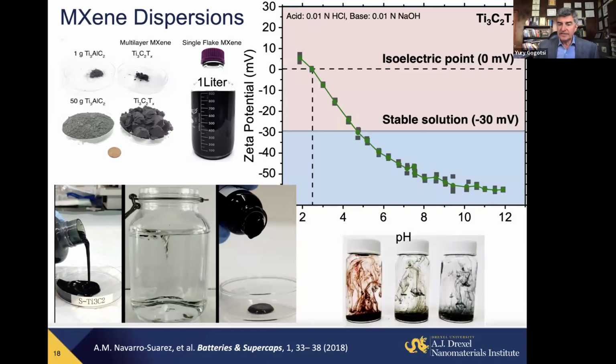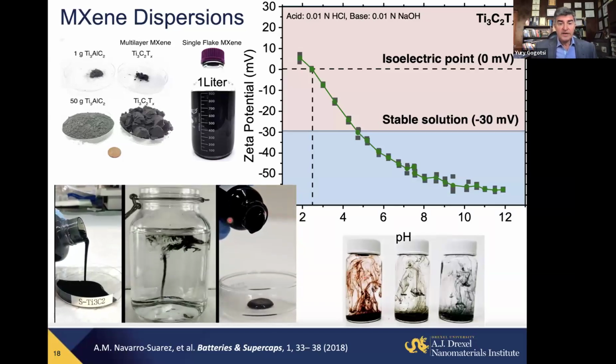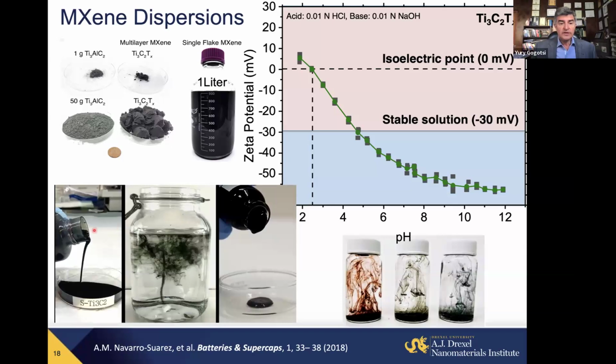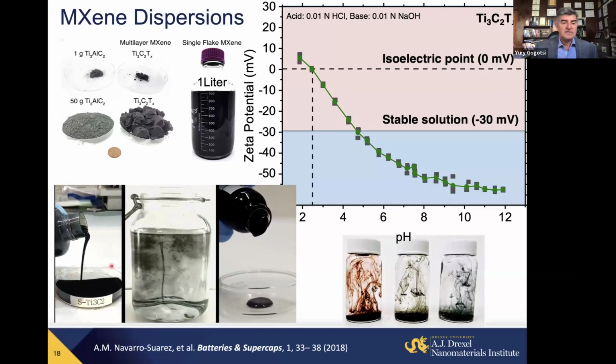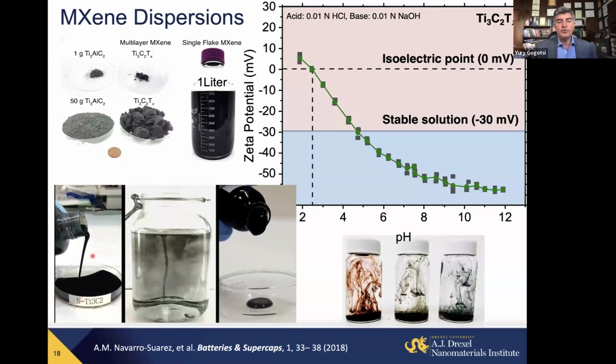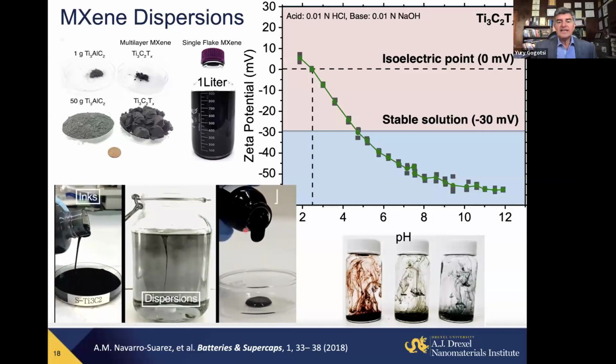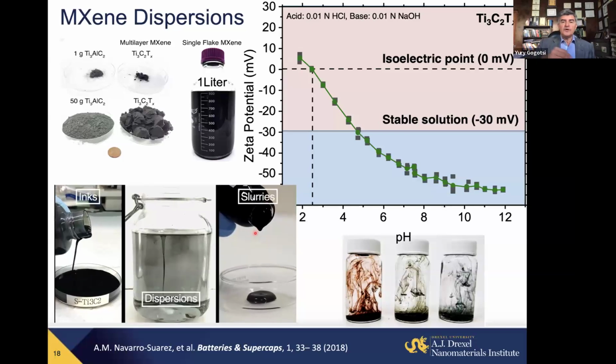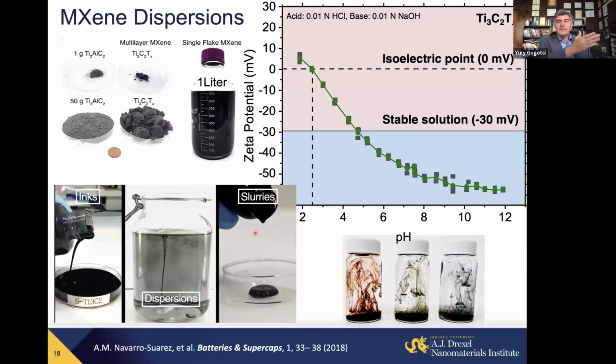It can come in different colors because different MXenes have different optical properties. You saw it on my first slide. Moreover, if you have a solution like that, you can use it, for example, to spray the walls or do inkjet printing. If you concentrate it, you will get a liquid crystalline solution. You can draw fibers, or you can make films by doctor blading. But again, just flakes of MXene in water.